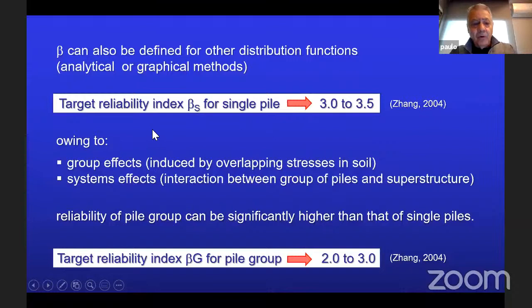According to Zhang, 2004, the target reliability index beta S for a single pile should be in the range from 3 to 3.5. And owing to group effects, pile group effects induced by overlapping stress in soils and other causes, and also system effects, the interaction between the group of piles and the superstructure, the reliability of a pile group can be significantly higher than that of single piles. This is what you know. And the target reliability index beta G for a pile group should range between 2 and 3, also according to Zhang.